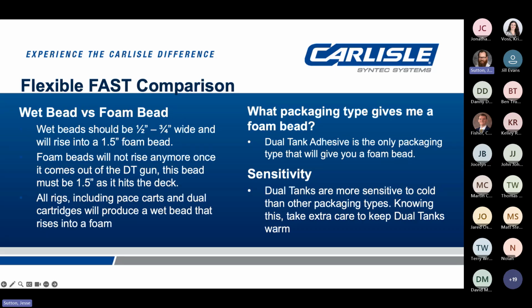Dual tanks, however, do not rise. The material comes out as a foam already, and it doesn't really get bigger than it comes out. It will puff up a little bit, but it's not a difference of a full inch or 3/4 of an inch. So we want to see a much thicker bead when you're using dual tanks, and we always want to end with a 1.5 inch foam bead. Just keep that in mind as you're applying this stuff, no matter the time of year, but especially in the wintertime. As I mentioned already, the only packaging type that we have that's going to give you a foam bead is the dual tanks. That's pretty true of the industry as well.